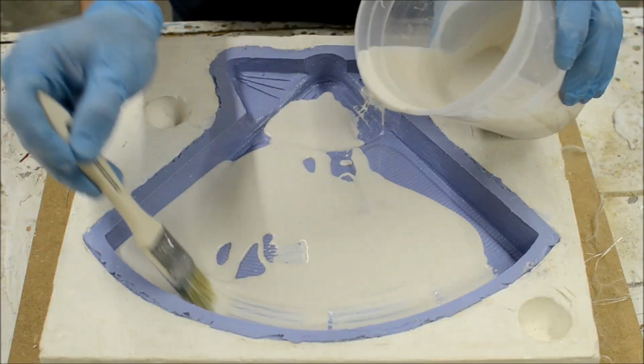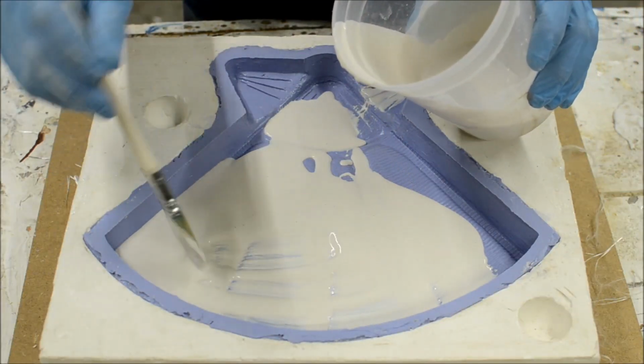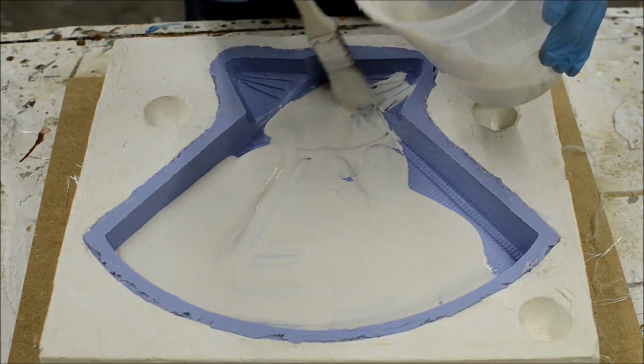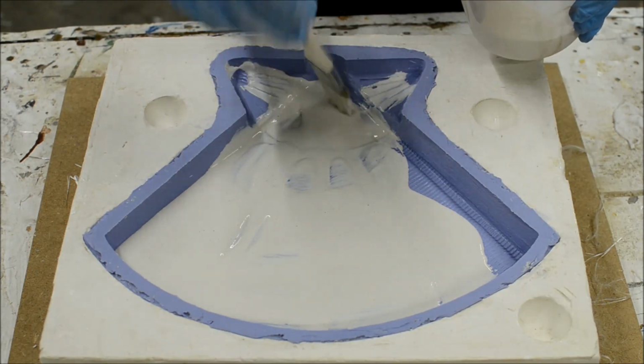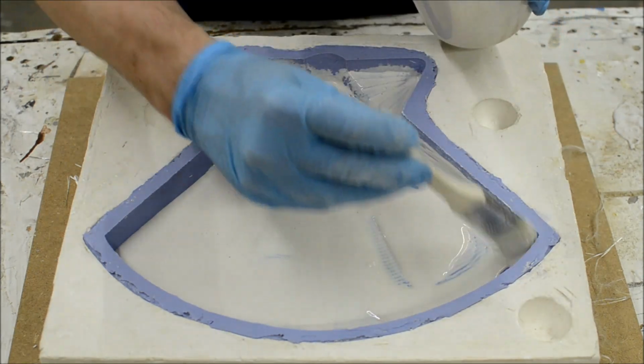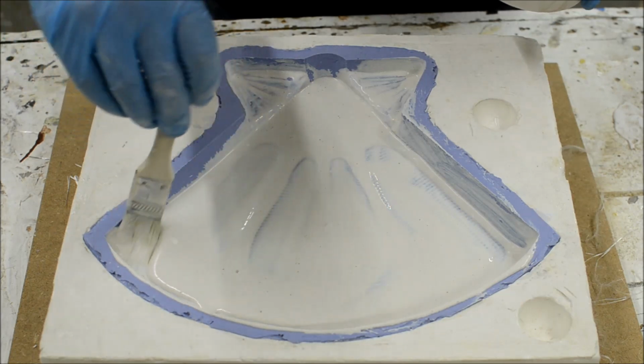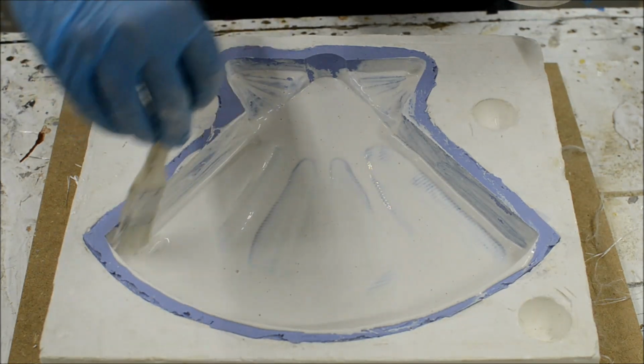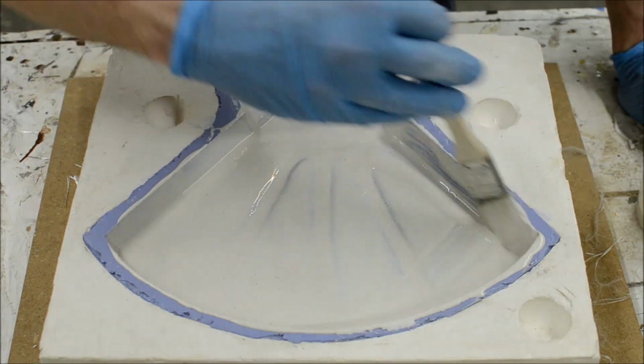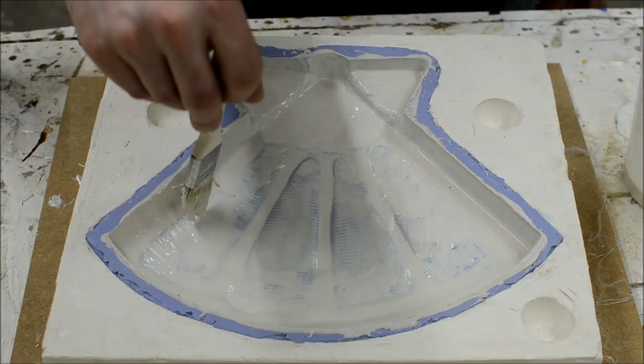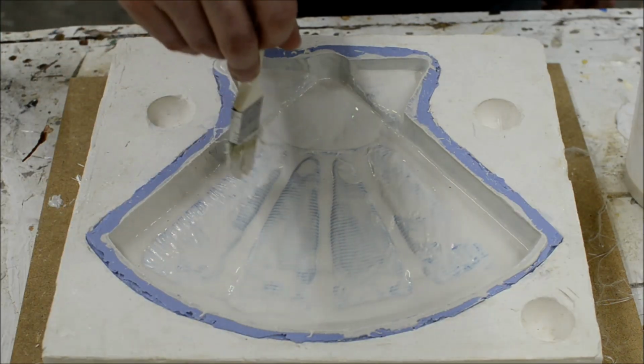When making fiberglass in a negative mold, lay down a surface coat of just resin. This will capture all the surface detail and help hide the texture of the fiberglass cloth. The resin may run down the vertical areas. Keep brushing it upward as the resin cures so you get adequate coverage.